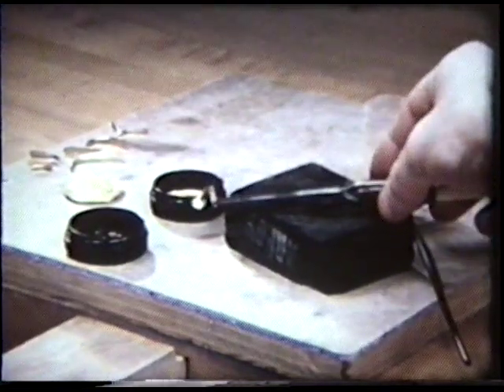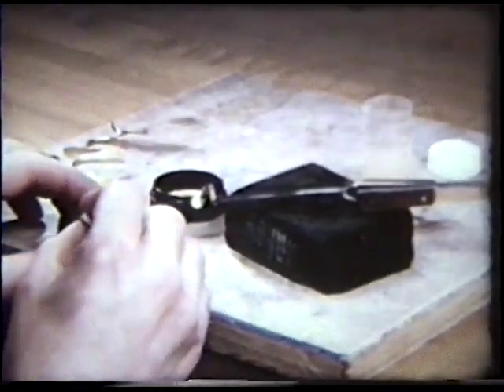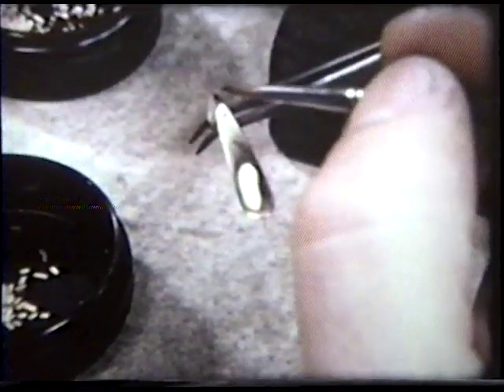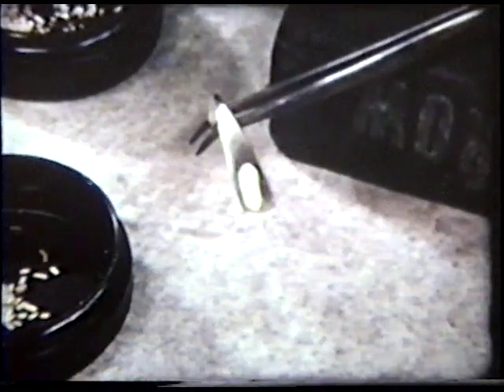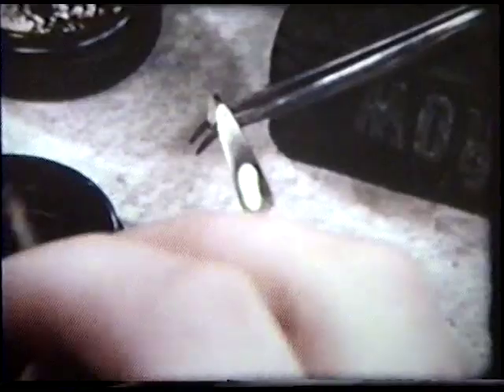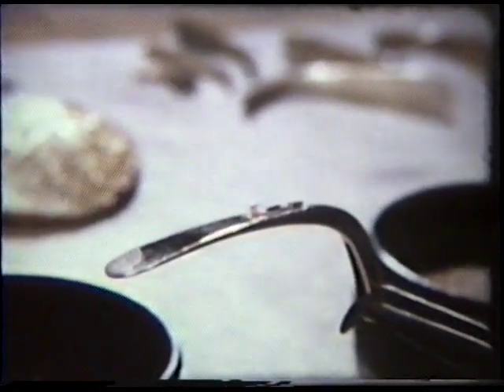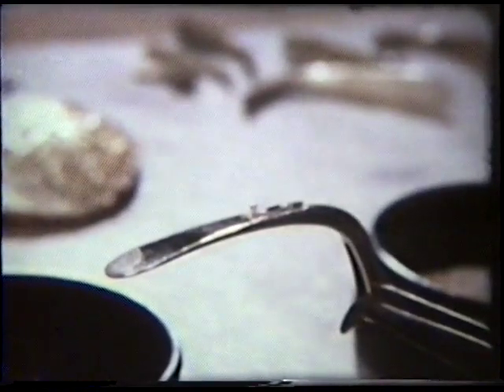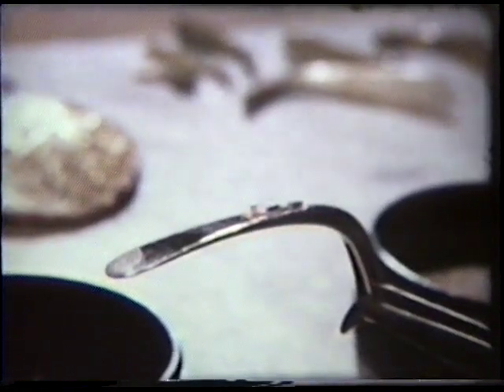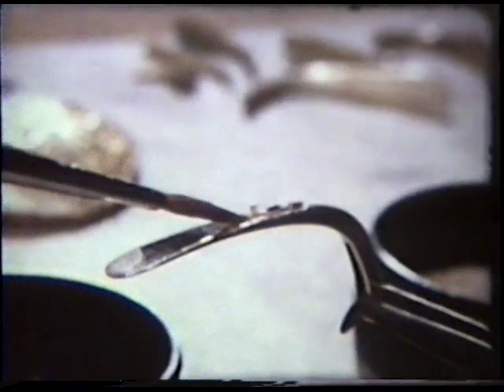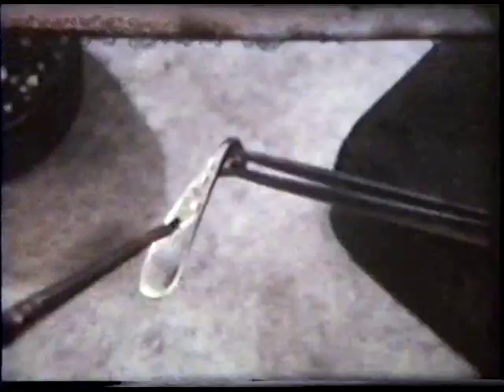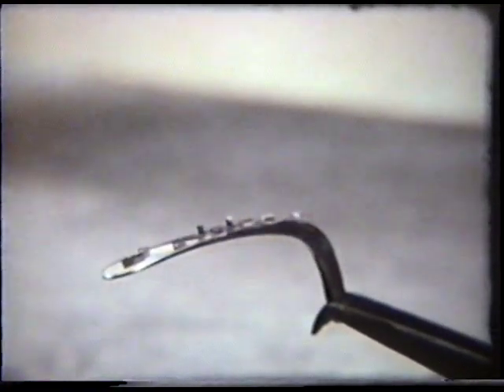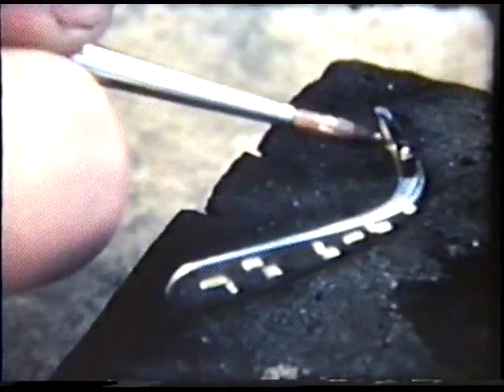A variety of sizes of rectangles of gold are positioned to provide accents to the line of the leg. These are fused in place by a slightly different process from the one used on the back. Since the 18-karat rectangles are to be attached to a 14-karat base, the base has a lower melting point than the rectangles, and a small pointed flame is used to concentrate the heat at the joint. Flux in the glue keeps the joint from oxidizing and allows the pieces to be welded together.